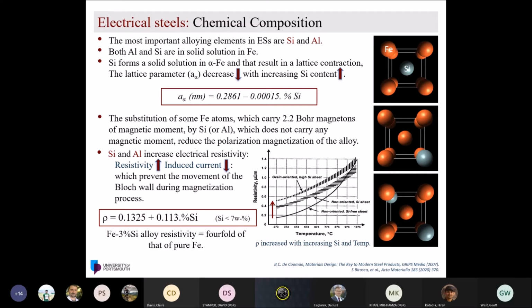Now I'm just showing here, I don't have a pointer on my side. If you look at the graph here, you will see how the resistivity increases as you add more silicon, from non-oriented low-silicon steel upward. This is again one of the equations we use for how much the resistivity will increase. If you use this equation, you'll find that by adding only 3% of silicon, you increase the resistivity of the silicon steel to fourfold that of pure iron, and that's important to know.